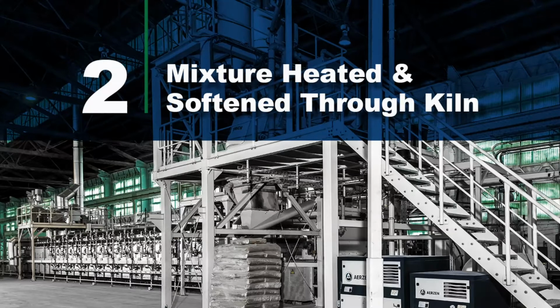All right, and those temperatures are all related to the science of being able to foam the glass properly, right? So the first thing that we want to do is soften the glass. Next thing is we're activating that foaming agent to create an air bubble. We're sintering the glass powder around that air bubble in order to trap it. And then we're heating it to expand the air bubble in volume. Okay, so different temperature zones could range anywhere from, say, 600 degrees Celsius all the way up to about 1,000 degrees Celsius, depending on where you're at inside of the kiln.